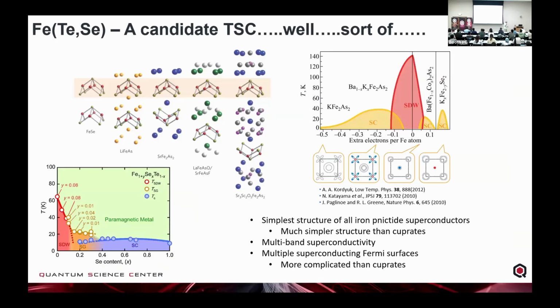For the sake of time, I'll run through these last few slides quickly, but I want to give you a sense of an example of how we deploy these techniques in the Quantum Science Center for some of our materials of interest. One of the materials that we're really interested in is this compound of iron, tellurium, selenium. It is a member of the iron pnictide superconducting family, which is similar to the cuprate superconductors but does have more complicated Fermi surfaces, because the Fermi surfaces will change as you start doping and controlling the electron count. This iron, tellurium, selenium is the simplest of the structures, but now we can take the selenium and start doping it with tellurium, and you can see a lot of the behavior of the superconductivity in these materials.